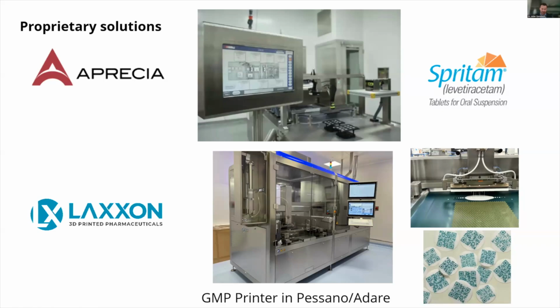They disintegrate very rapidly, and they are using a proprietary, highly developed binder jetting process that can be used continuously. They have developed this further to also print in blisters right away to also get a nicer surface finish. So quite advanced where they are. A completely different approach is presented by Laxxon Medical, shown here on the bottom. They are using a screen printing approach. So additive manufacturing using screen printing, the same technology that is used to print colorful prints on t-shirts, really squeezing ink through a screen multiple times on top of each other.